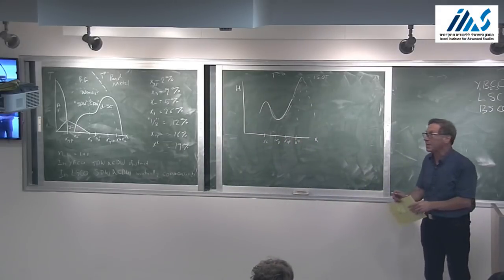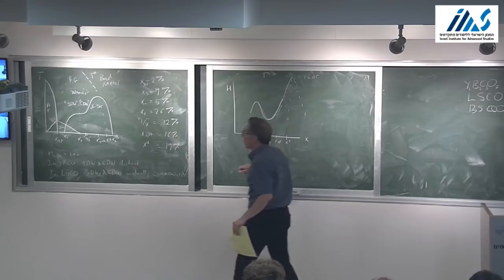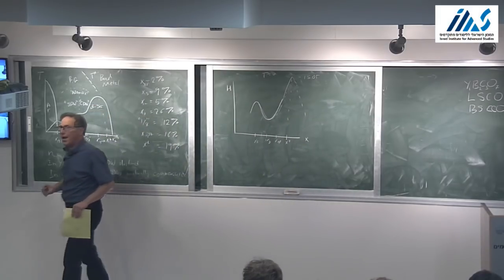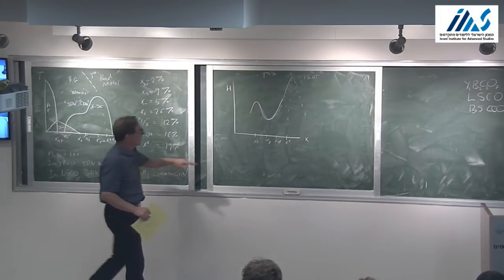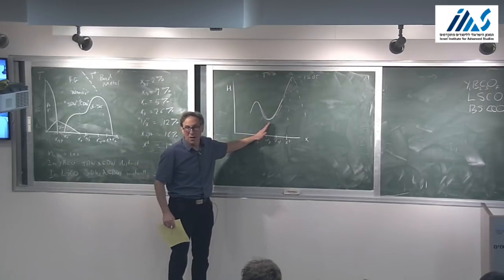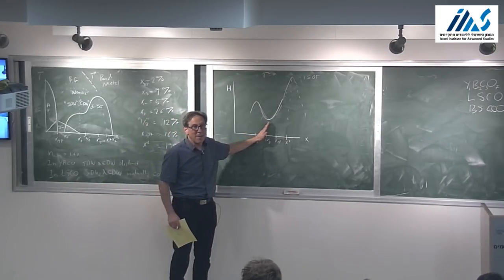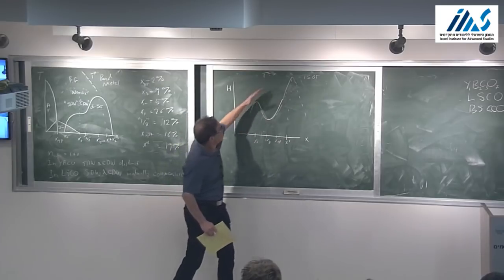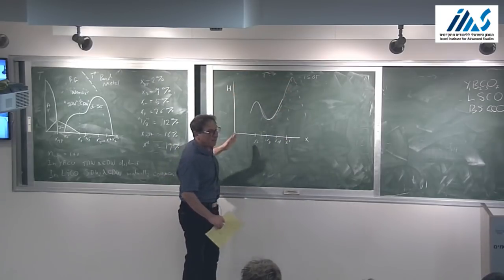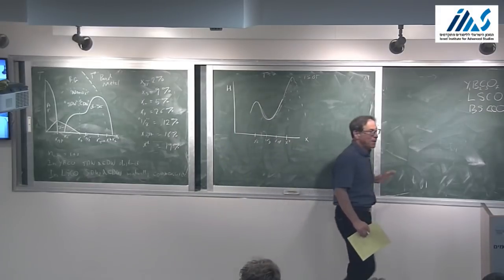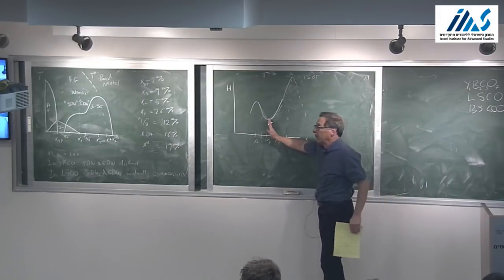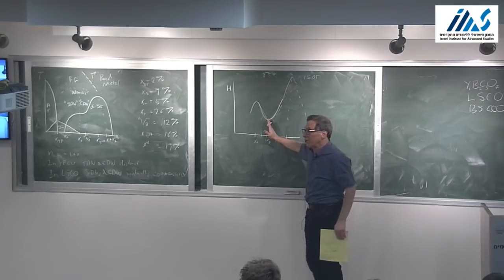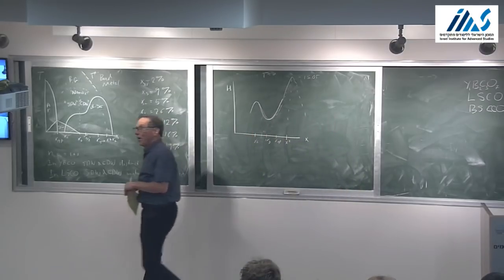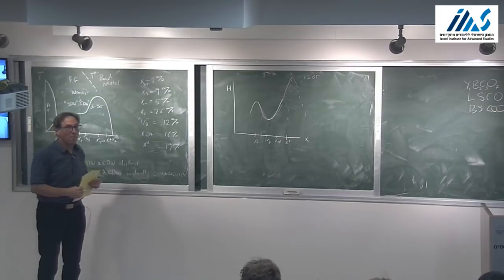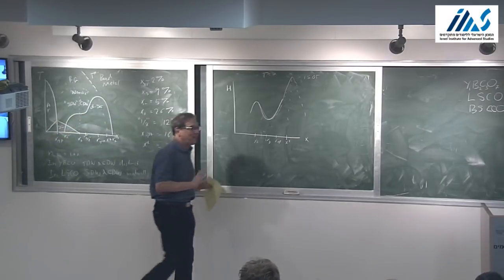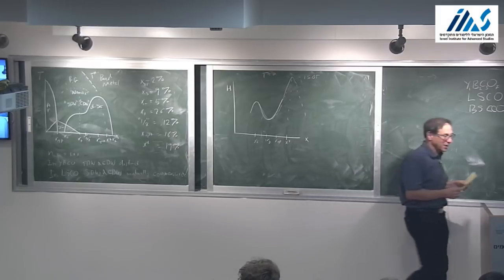quantum critical points. The other thing is that it turns out that charge density wave order is anomalously stronger near 1/8 doping, and that maybe what's going on here is there's some sort of more simple dome-shaped HC, but then there's an anomalous suppression of HC due to competition with another phase at 1/8 doping. And there's evidence in favor of both of those propositions.